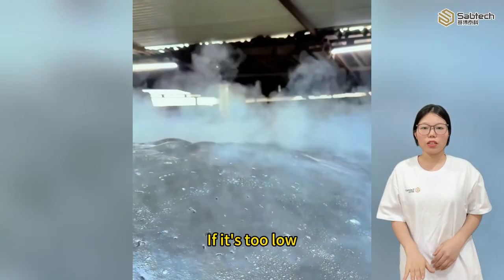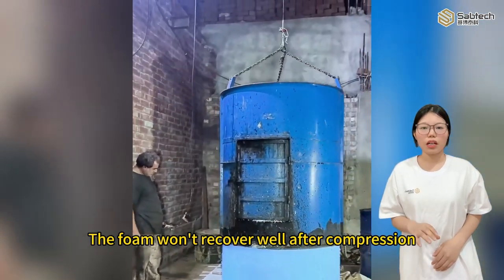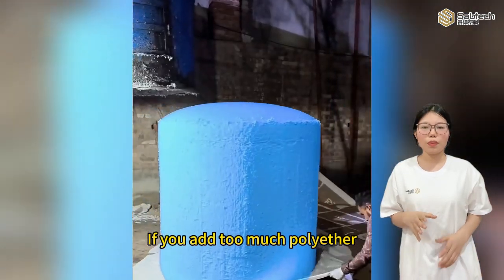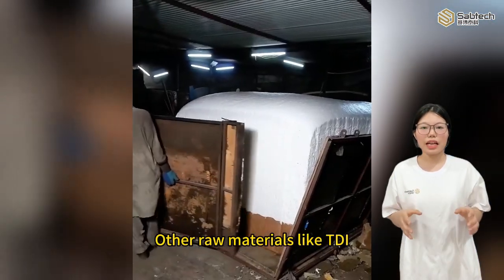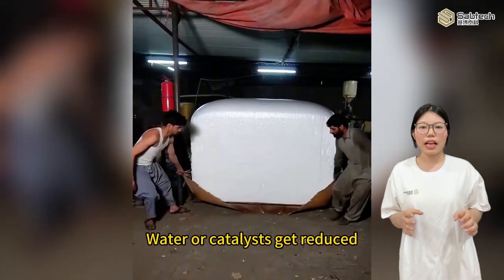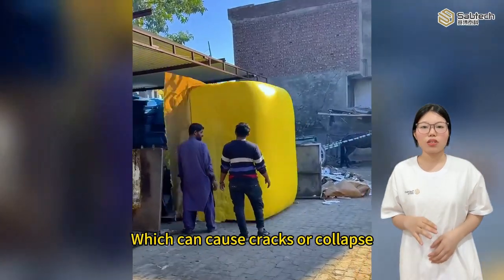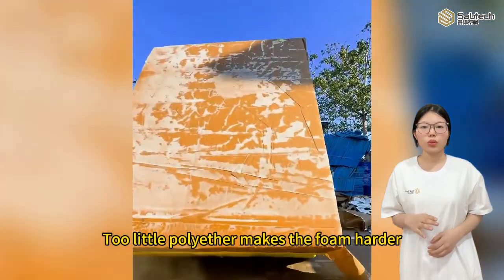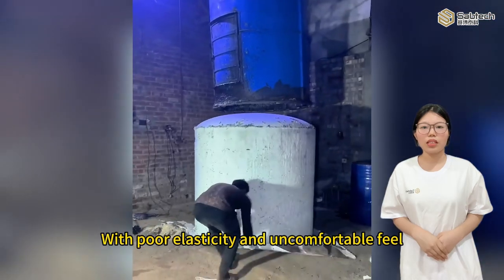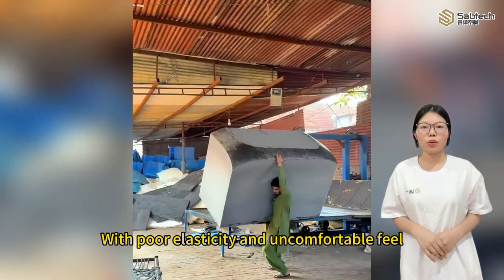If it's too low, the foam won't recover well after compression. If you add too much polyether, other raw materials like TDI, water, or catalysts get reduced, which can cause cracks or collapse. Too little polyether makes the foam harder, with poor elasticity and uncomfortable feel.